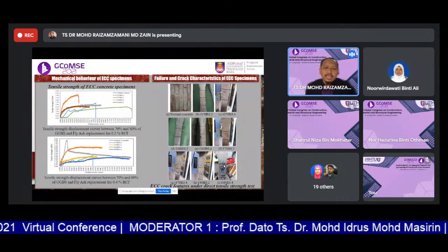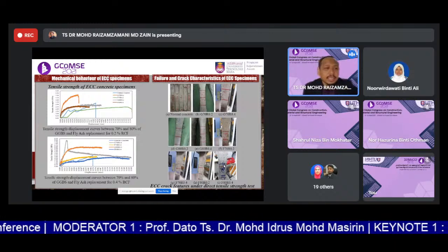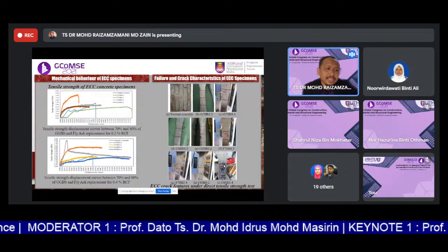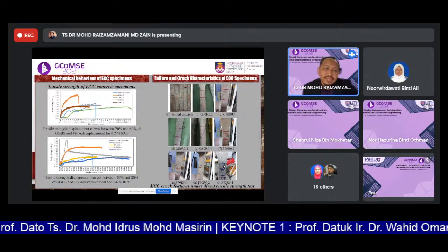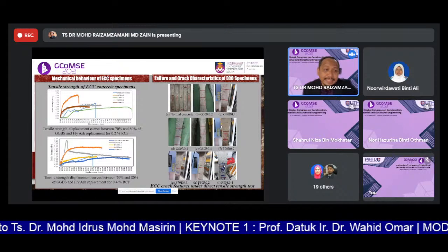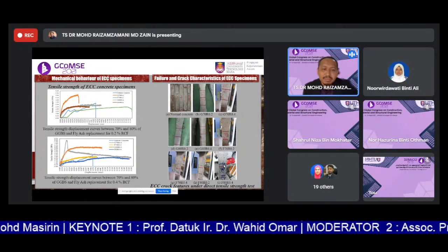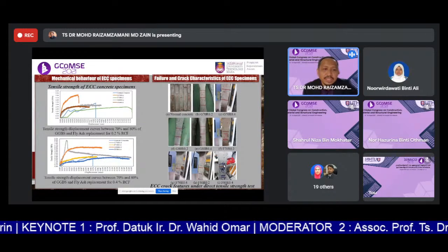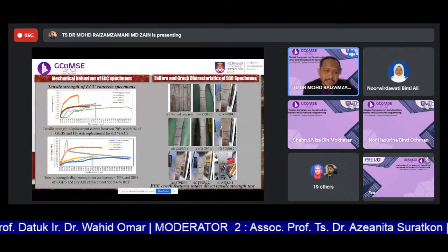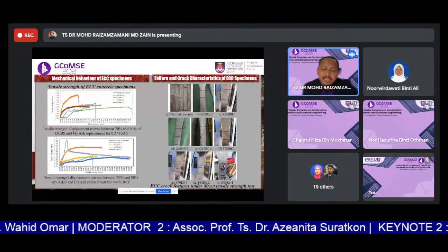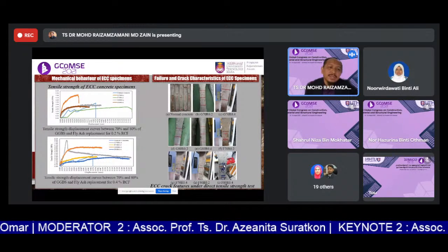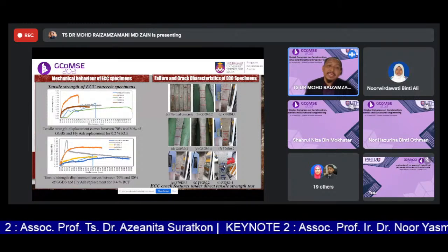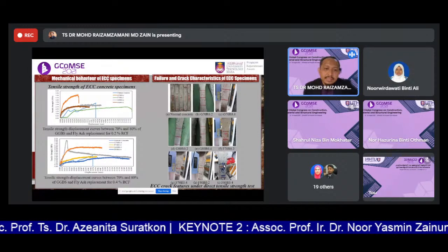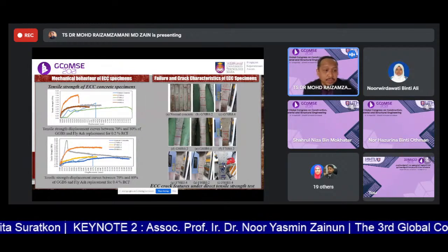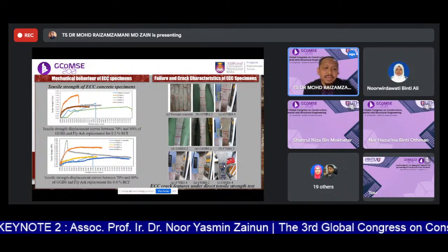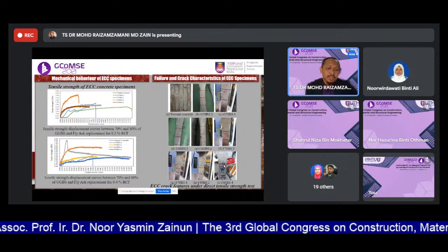And then if you look at the second figure here, it indicates that GGBS cement combinations for G70 0.4 seem to have the higher tensile strength values of around 8 MPa when compared to the fly ash cement combinations and normal concretes. So this shows that the tensile strength of the mixtures containing 0.4% RCF with 70% GGBS cement combinations is significantly greater than the tensile strength of the mixture containing 70% fly ash cement combinations and also the normal concretes.